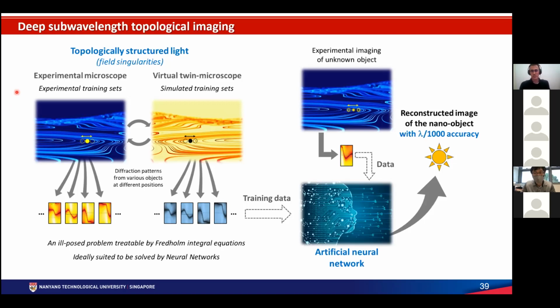You start with topologically structured light. How do you generate it? You interfere coherent waves, like laser light, with a metasurface or a spatial light modulator, or you might think of generating it directly in the near field with a source that is structured to generate topologically structured light in the far field. Then you illuminate an object, you change the position of either the object or the field, and you generate a certain number of scattering events. What you need to know is that the inverse scattering problem is an ill-posed problem, which is treatable by integral equations, which are ideally suited to be solved by neural networks. So once you generate enough training data, you can feed it to the artificial neural network.